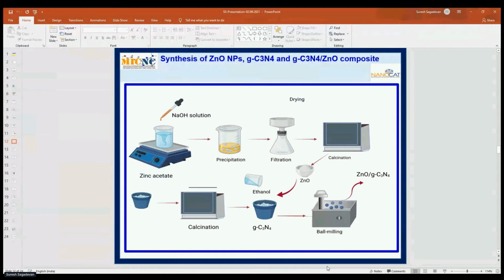First we synthesized zinc oxide nanoparticles. You can see here in the slides, a 1 molar zinc acetate dihydrate solution was made up to 50 ml, and then 50 ml of sodium hydroxide solution was added dropwise with continuous stirring until we see the formation of a large quantity of precipitate. The stirring was continued with this precipitate for another 18 hours. After this period, it was filtered to obtain the precipitate, washed with distilled water several times.